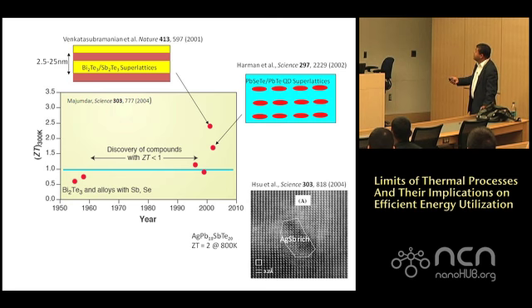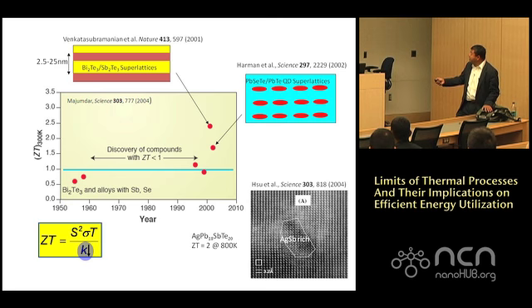So they saw this and said, okay, nanostructures does increase your ZT, just like Dresselhaus predicted. But what they found was that instead of increasing the S squared sigma, the electronic side, which was the prediction, it increased ZT because of a reduction of thermal conductivity. In all of these cases, except for one, the thermal conductivity went down. It had nothing to do with the electronics. In fact, in some cases, the power factor went down, but the thermal conductivity went down even further. So it turned out to be a heat conduction problem. Eventually, that was the outcome of this.